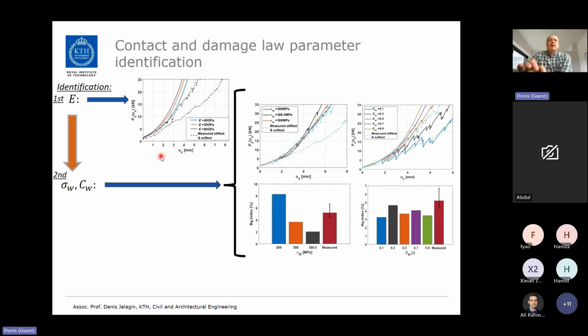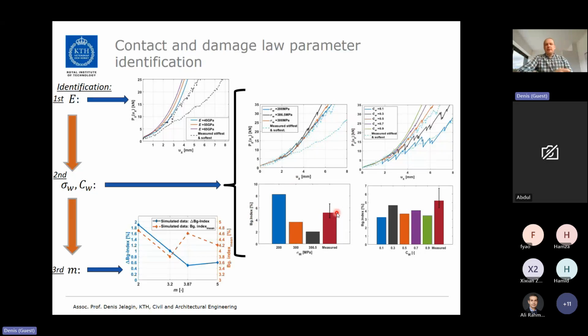Once this is done, we can go further and identify the failure law parameters, Weibull stress and weakening coefficient. Those parameters are identified by fitting the rest of the force displacement response and the so-called breakage index shown here. The breakage index is a measure of deviation of the gradation curve after the test as compared to the gradation curve before the test. The bigger the deviation, the more aggregate breakage we had. The 3 bars here are the results of our parametric study, and the red one is from the experiment. And finally, we can determine the Weibull exponent. Everything is, of course, statistical with unbound materials, so we also have a parameter controlling the width of the Weibull distribution, and we determine that by trying to match experimental and numerical scattering.